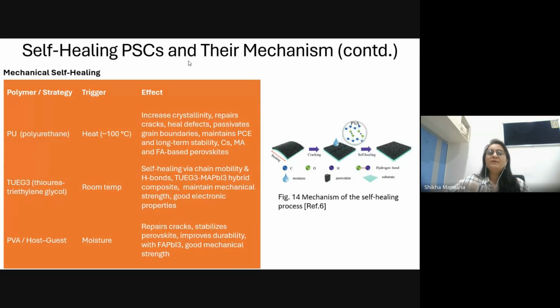If I say in terms of self-healing perovskites, in terms of mechanical self-healing, if there is any problem, because here we have some flexible perovskites. Here also we have similar polymers, as I've discussed when discussing the exposure to moisture. So here also, when they are triggered with heat and there is any bending happening in the material, or there is any crack, if I use this particular material, PU, polyurethane, then it can combine with my particular perovskite, and after some time it will start to self heal itself.